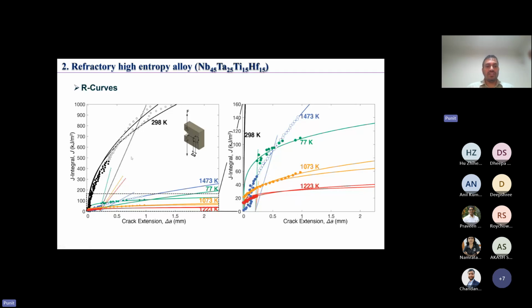So the existing method of using elastic compliance or unloading compliance to measure crack length was not really working. So we had to use the normalization method, which is mentioned in ASTM E1820, to get a JR curve at higher temperatures. If you zoom in on this region, at room temperature you can see the R curve goes really steeply up, and after this value we did not have a valid J value, but even here the J value has almost reached 500 kilojoule per meter square.